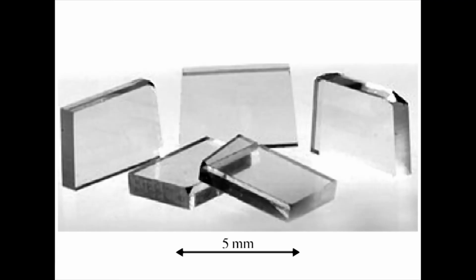The actual conditions required for making each type of diamond are very similar. It is the choice of substrate that determines which will grow. For single crystal CVD diamond, the substrate needs to be single crystal diamond, and the new diamond film grows epitaxially, with the deposited film taking on the lattice structure and orientation identical to those of the substrate.